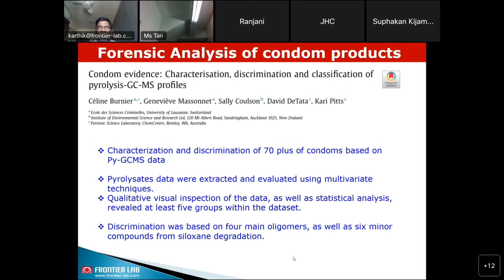Then you need to have a large data set that can be used for statistical analysis through different multivariate techniques, because otherwise it will be a lot of work to really interpret the data. When you develop such a data set, these days the solution providers are providing such a database with a library that can be used for your data interpretation. Here, as research work, they treated this data on their own through different statistical tools, and the results helped them to discriminate these samples based on the four main oligomers found in different condom samples, and also the six minor compounds from the siloxane degradation.